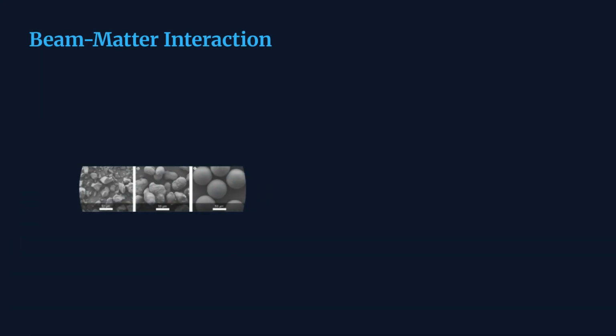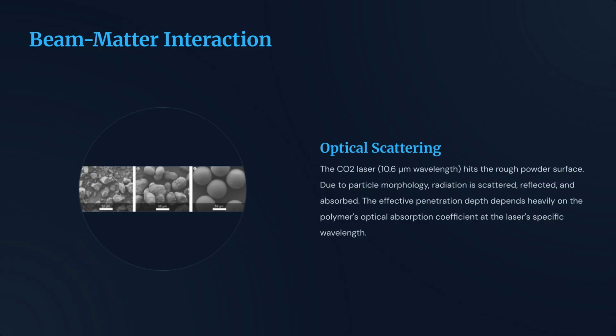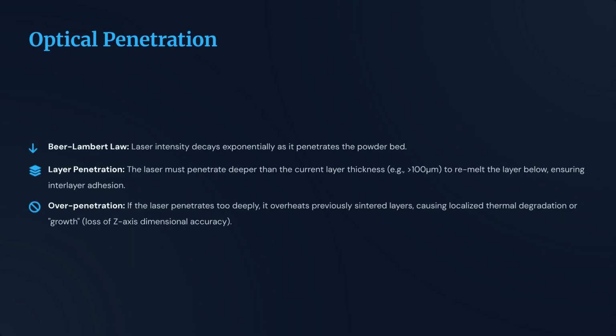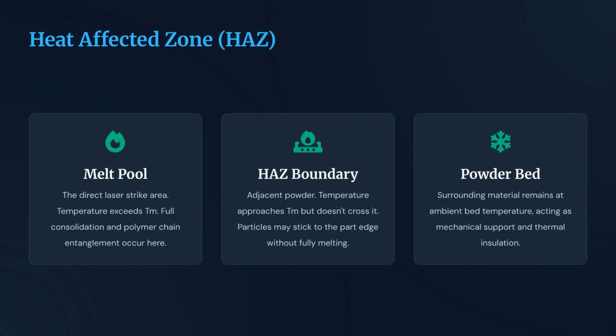Beam-matter interaction is crucial. When the CO2 laser strikes the rough powder surface, particles scatter and absorb the radiation. Penetration depth is determined by the polymer's optical absorption coefficient. We must manage optical penetration carefully. The laser must penetrate deep enough to ensure interlayer adhesion, but over-penetration can cause overheating and degradation, leading to a loss of dimensional accuracy.